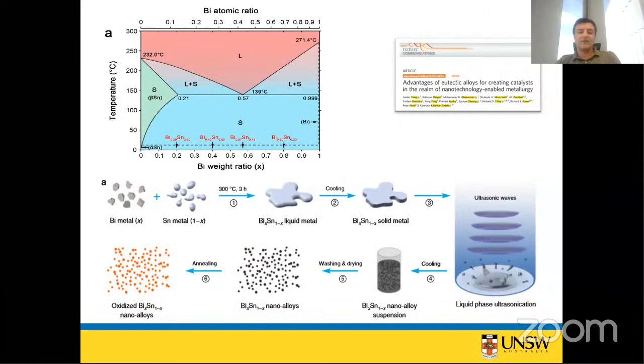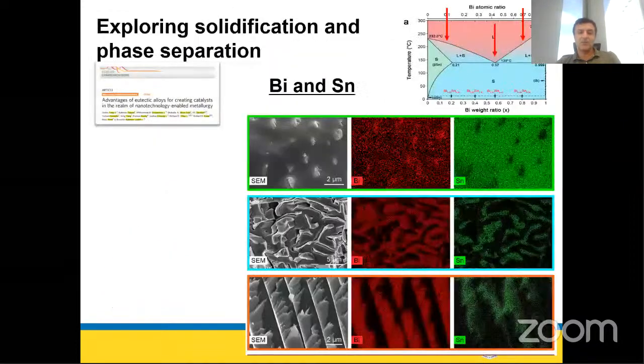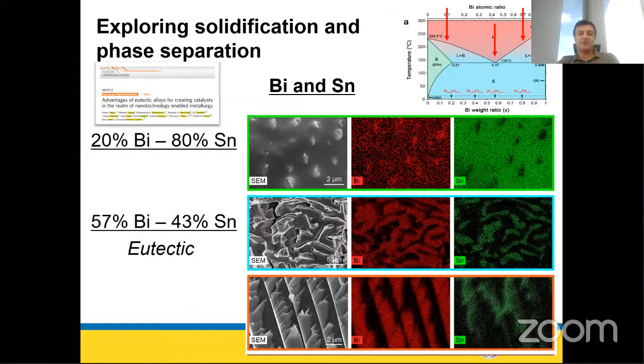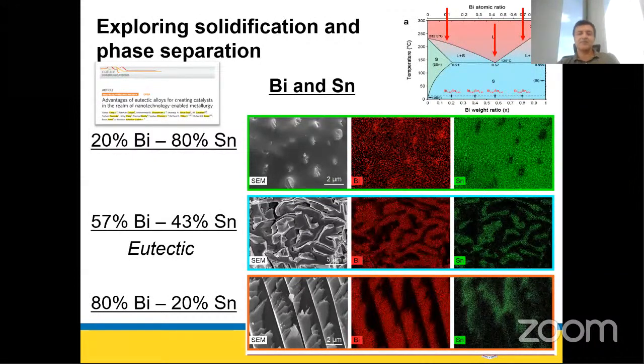And if you sonicate it, you can make these nanoparticles of bismuth tin, and we look at it. Now, if you just shake it a little bit and make larger droplets, millimeter droplets, and you open them up, you see very interesting properties and structures. You have lots of tin and 20% bismuth. You see these oceans of tin crystal at the background, and you have rods, very well organized rods of bismuth, crisscrossing them. Then we have 20% tin and 80% bismuth. Then we have planes of bismuth and tin crisscrossing each other, and they're highly crystalline planes.